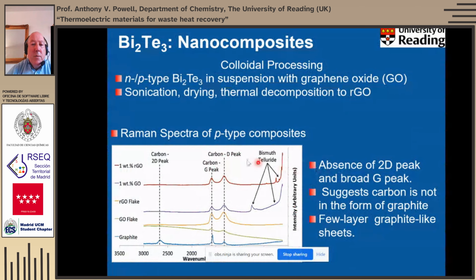And we can follow that process using Raman spectroscopy. So this curve right at the very top here, for instance, is a 1% reduced graphene oxide bismuth telluride composite. The important thing to note really is that this carbon 2D peak, which is present in graphite, is not present in the composite. And also this carbon G peak, which is very sharp in graphite, is broadened considerably. And you'll notice the intensity ratios of these two peaks have swapped around. So all of those factors together suggest that we don't actually have graphite there. We don't really have graphene there either, as far as we can tell, but we probably have few-layer graphite-like sheets. So it's somewhere between bulk graphite and single layer graphene.